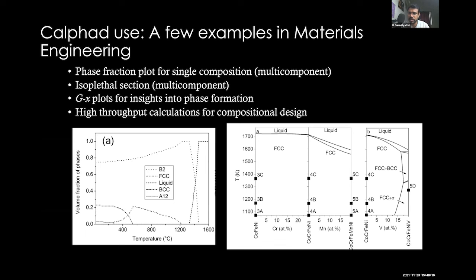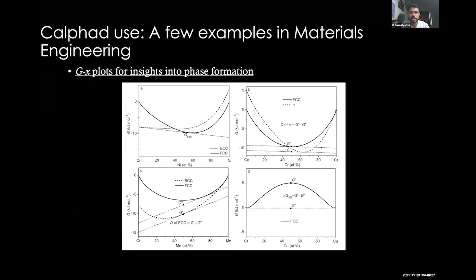Of course, there is an extra dimension. Temperature is also there. 6 dimensions are there. So this is the way that the high entropy alloy community uses. So yeah, this is about Gibbs energy composition plots of binaries, chromium nickel, cobalt chromium. For them, we can only plot Gibbs energy composition plots. And from that itself, we can get some insights about which phase will be stable in the microstructure or not. So this is one paper of mine where the method is explained in detail.